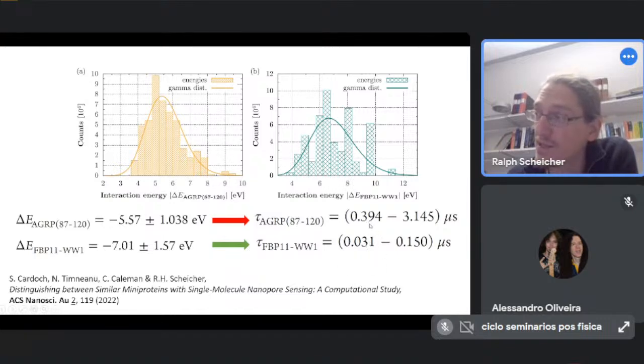So this should be distinguishable. I mean, the duration of the signal should be able to distinguish because it's orders of magnitude faster in one case compared to the other case. And it actually spreads out quite a bit. So it spreads out over one order of magnitude, but the overlap is almost non-existent here in the translocation times.